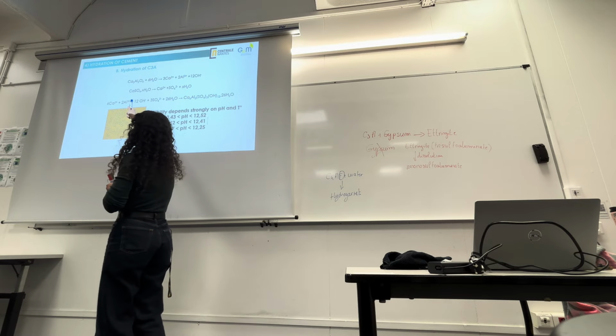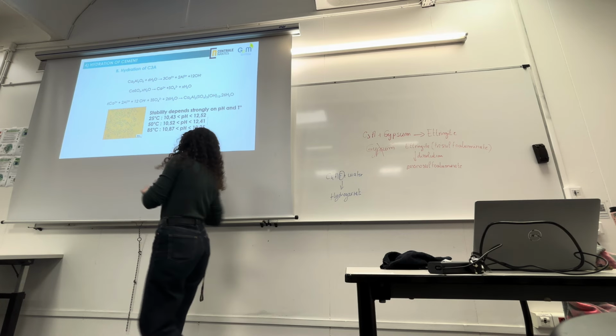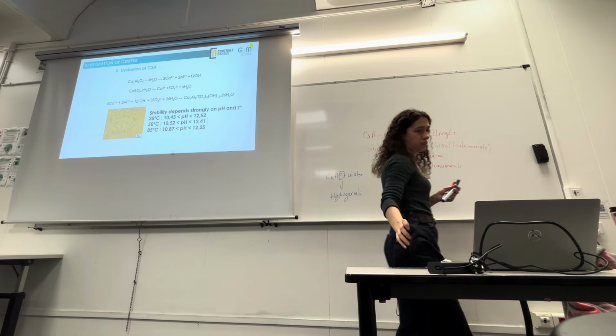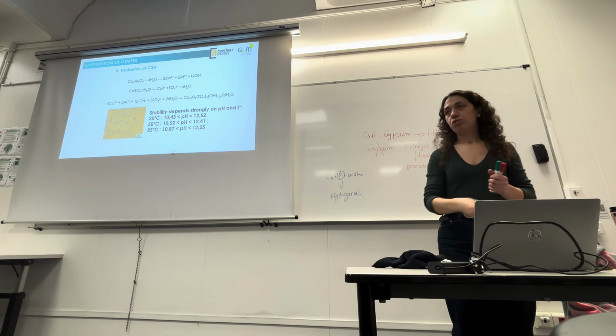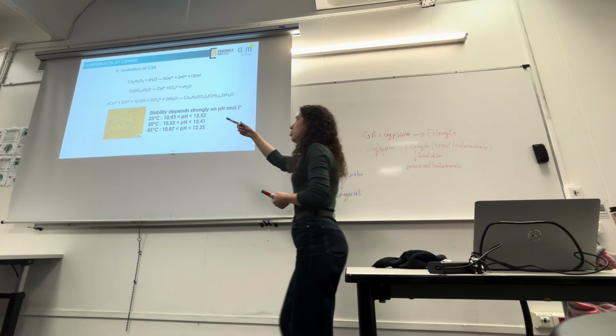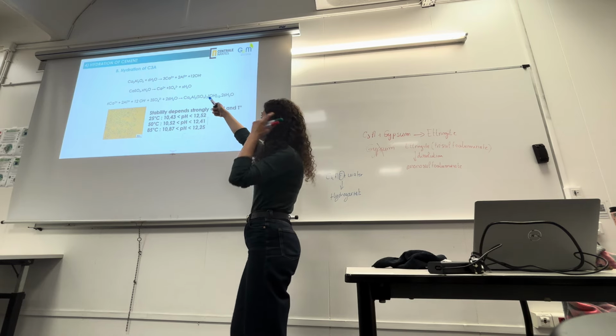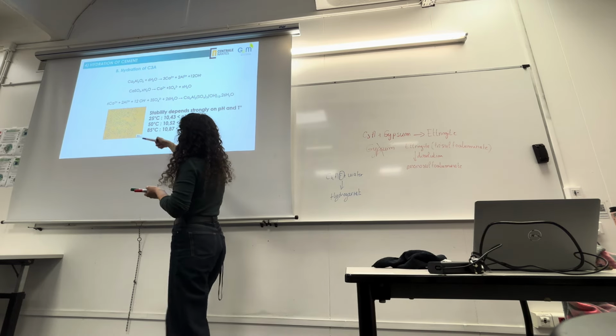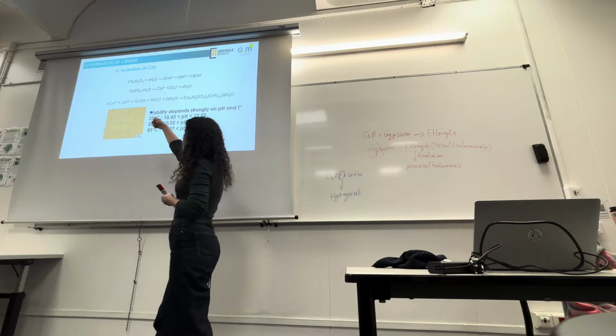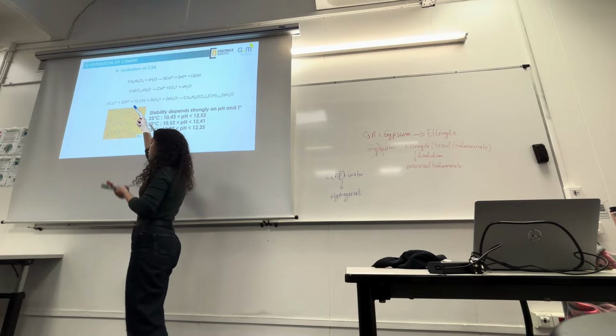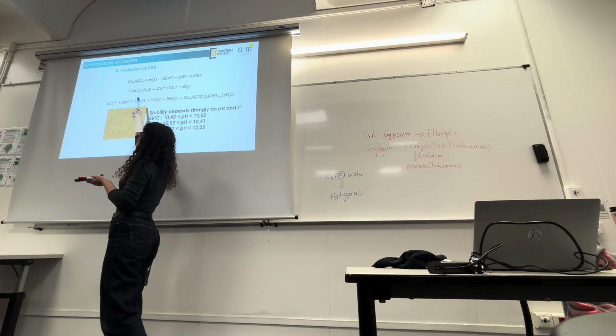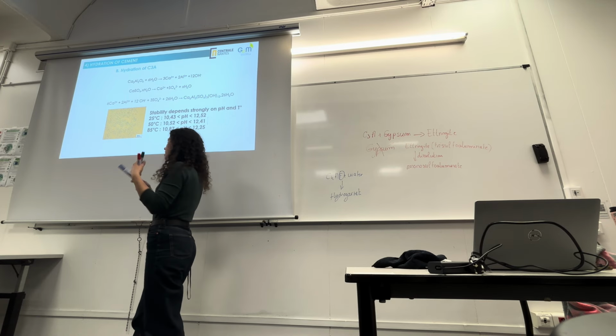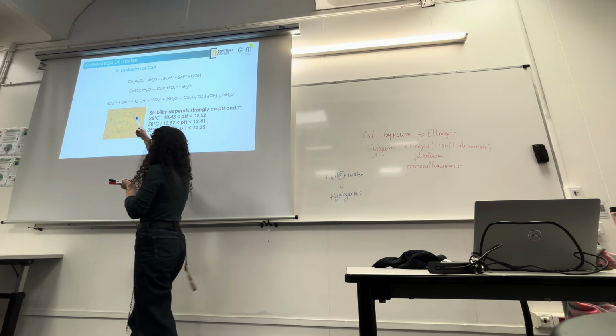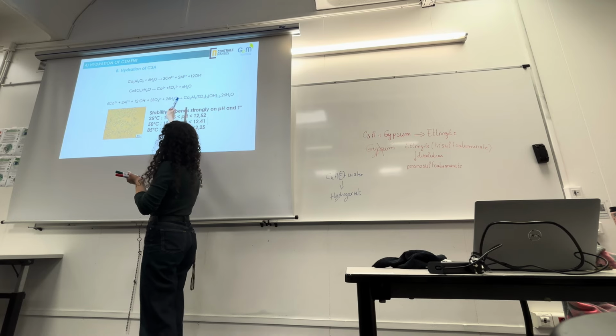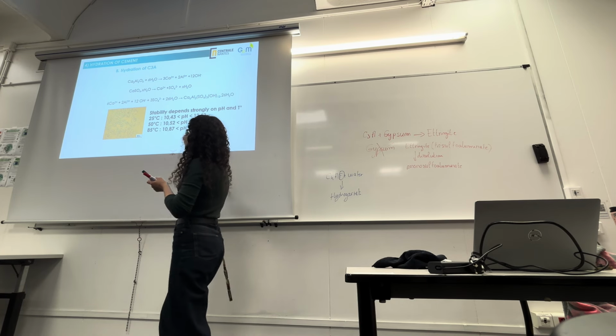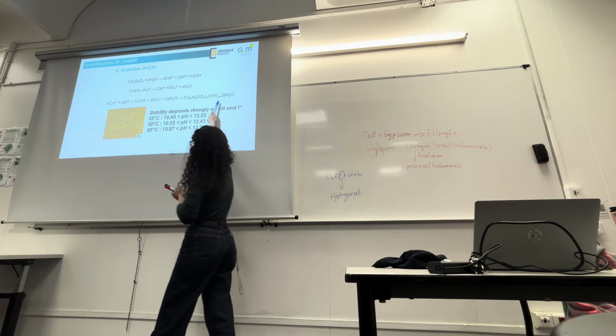We have the dissolution of C3A, that means reaction of C3A with water. So you have the ions in solution. You have the dissolution of gypsum. I put an X because it can be gypsum or anhydrite. We've seen that before. And you release sulfate in solution. And then all these ions will combine to form ettringite.